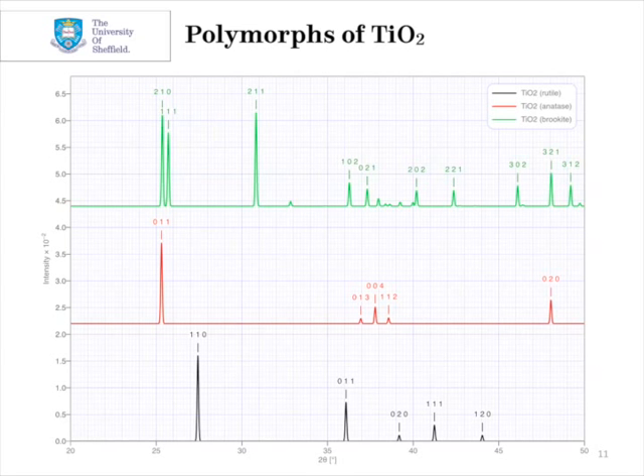But you can see that in each case the crystal structure is different and accordingly they produce very different diffraction patterns. So if you were to happen to pick up a jar labeled TiO2 filled with white powder, you would be able to do an XRD pattern and compare against these and work out what polymorph of TiO2 the jar actually contains.